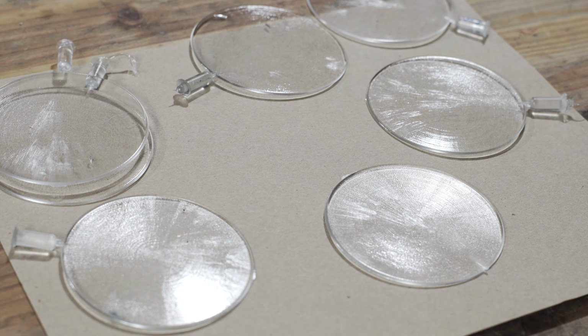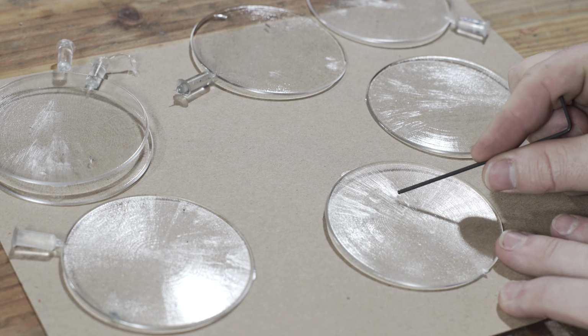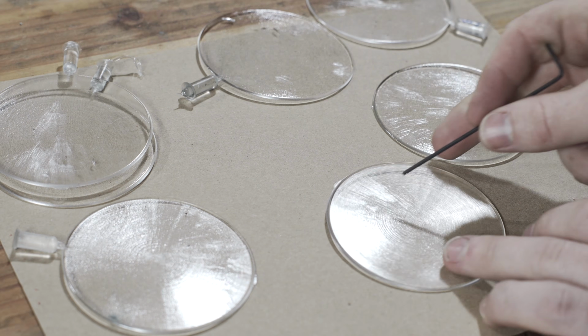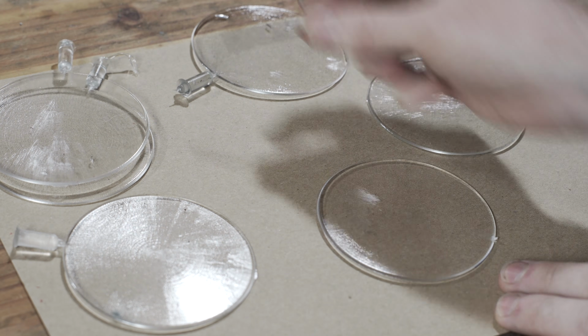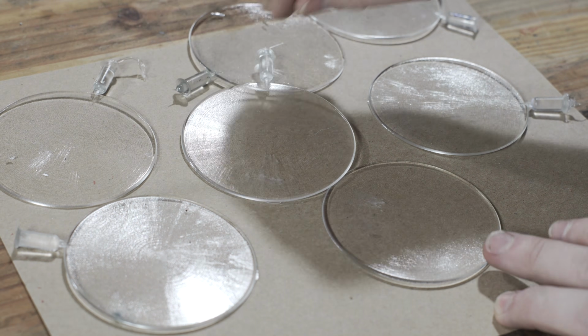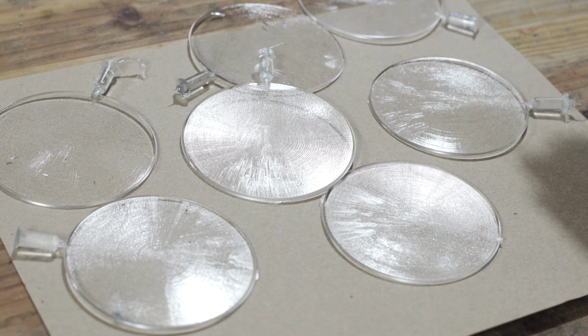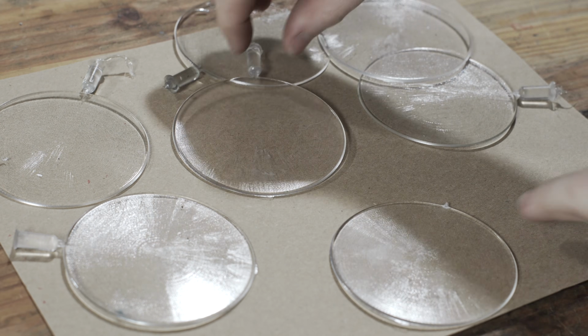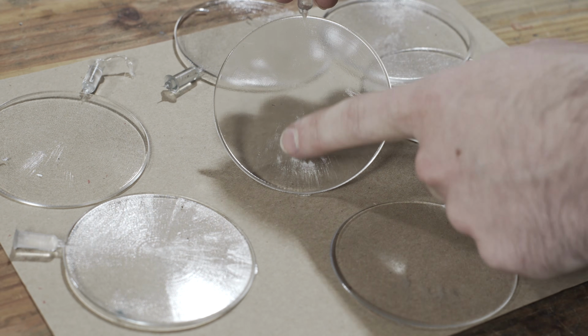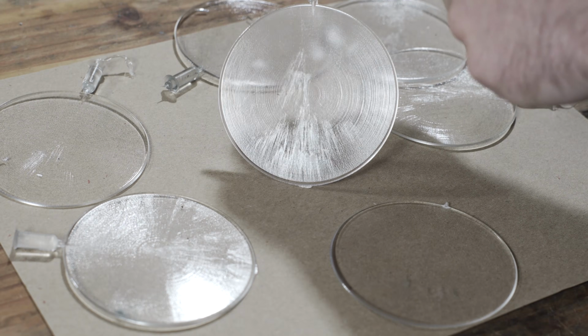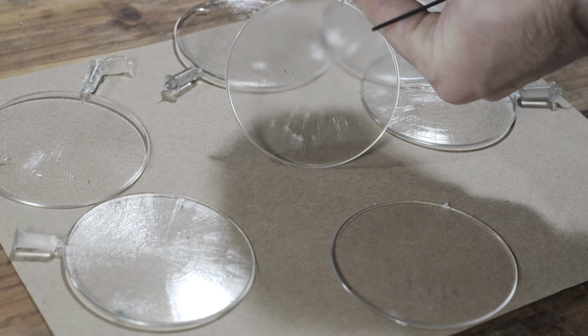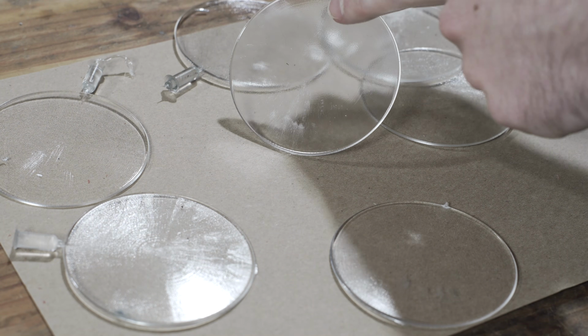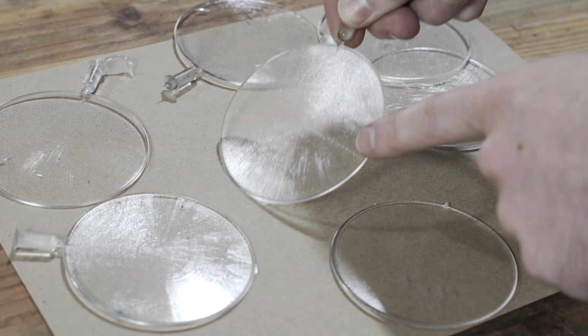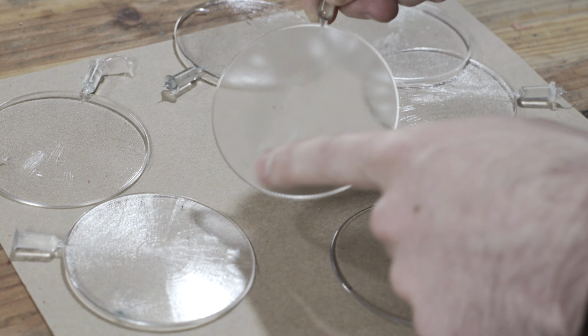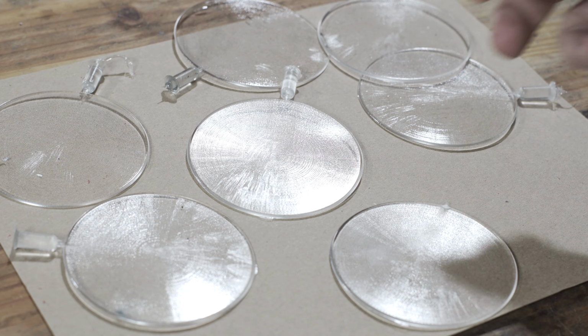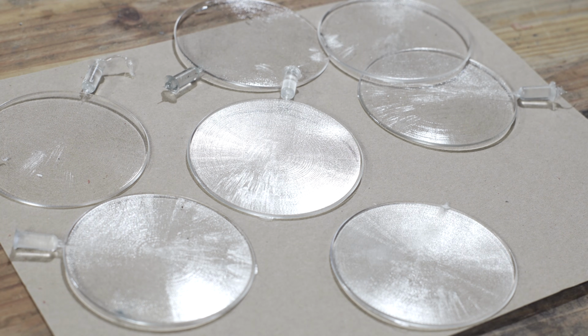The other interesting thing to note are these white streaks. You can see it here, and there's streaks here in a V shape. This one has streaks coming here. The way these always show up is coming down as the plastic's being injected. So coming from the runner into the gate, you'll get a radial splaying pattern, and it comes down like so. These streaks are called streaks or silver streak or splay.